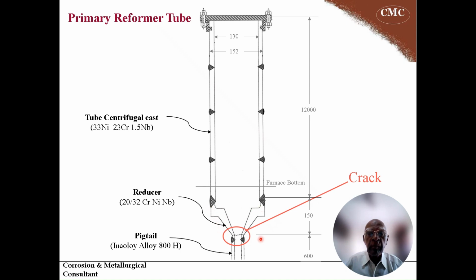reducer. Here is the reducer, and you can see it is reducing from the large diameter to a small diameter, and this has been giving the problem prematurely. It is a high temperature equipment, so the hot gases attack and lead to oxidation, and also because of size reduction stresses are developed, and reducers are under high duty of mechanical forces and also thermal forces. In a fertilizer plant, after some very short period of running, these reducers started cracking, and that is why this study was made in detail.